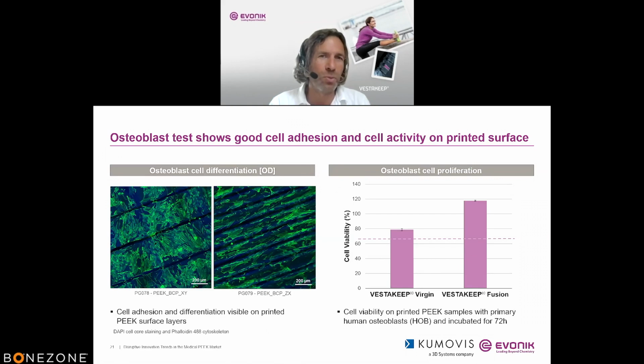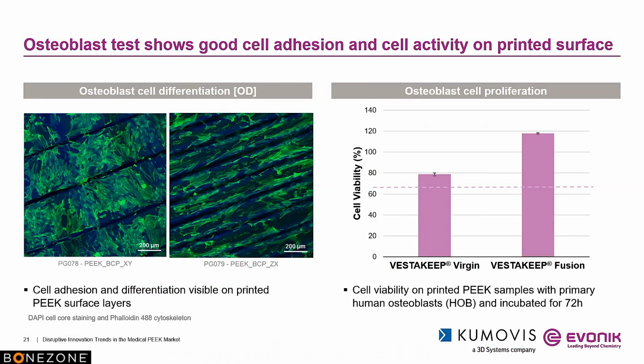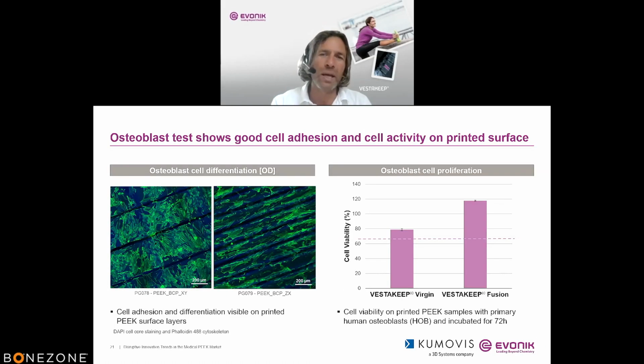Also there we did the osteoblast cell proliferation, and as you can see, a very nice adhesion of this osteoblasts on the surface, which show that the osteoconductivity, the BCP, is on the surface. And on the right-hand side on this chart, you see the improvement and increase of the cell viability compared with the virgin PEEK and our VestaKeep Fusion after 72 hours.